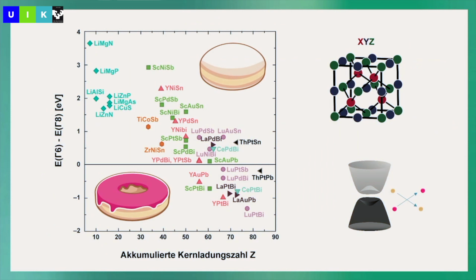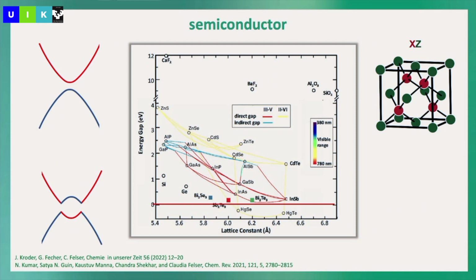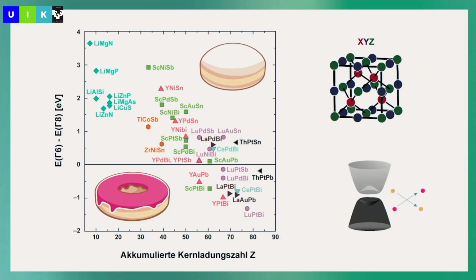my most favorite class of materials were the so-called Heusler compounds, where you can have silicon, then you can have gallium arsenide, like what Charlie Marcus likes, okay? The binary semiconductors, and they think they are doing ternary if they add a little bit of nitrogen into this. But then you can go to 3 elements and make semiconductors, and this was my concept, because here you can even make magnetic semiconductors much easier. And so it was obvious. And Shoucheng was very fascinated, because we can make many more compounds than mercury telluride. So we simply can have exactly the same band structure as normal semiconductor silicon with 3 elements, many of them, and we can have inverted band structure with a negative band gap with 3 elements.